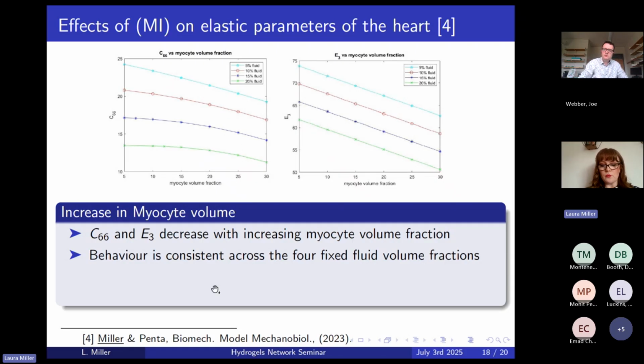So we see that when we have the smallest perfusion, we're still getting the stiffest result, through to when we have the highest perfusion, we are getting the softest result. So again, that tells us that the reperfusion is a good thing, but also that this homeostasis mechanism of the swelling of the surrounding myocytes is also doing a good job in bringing back that material compliance.